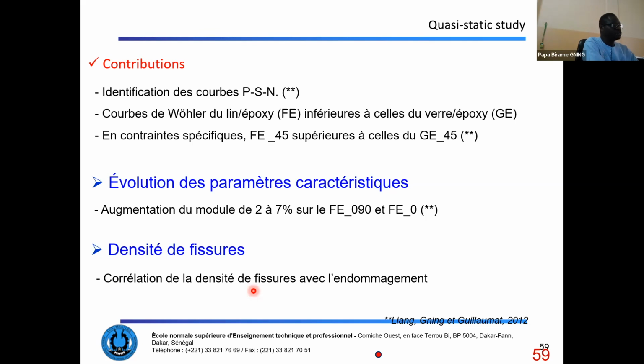We have seen that there is an increase of the rigidity of flax epoxy that can reach 7% when all fibers are along the loading axis, and it can be around 2% when it's a laminate of 0/90 degree fibers. The decrease of the increase of rigidity is attributable to the fact that in the 0/90 composite, you have half of the fibers oriented perpendicular to the loading axis, and in this direction you have important development of damage, and also an increase of the density of cracks inside the composite.